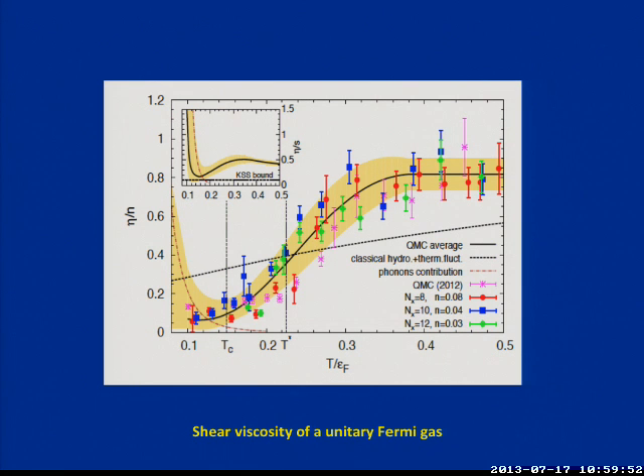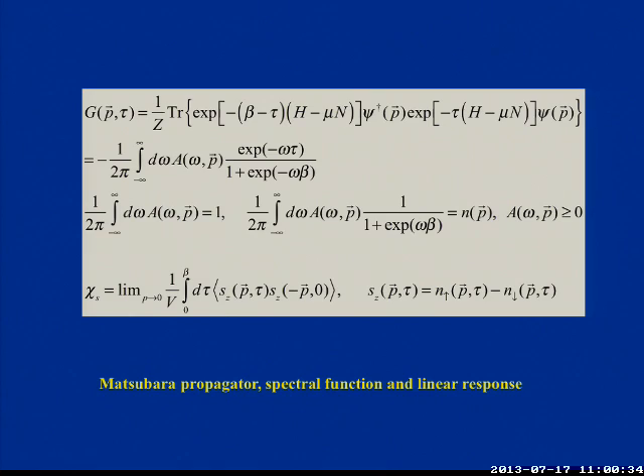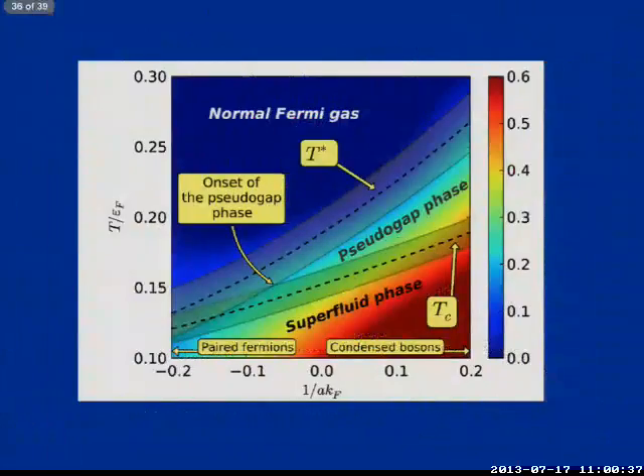One thing which was also calculated is the shear viscosity. You probably heard there was a lot of discussion, especially about the quark gluon plasma, after the work of Son and his two collaborators, that the shear viscosity has a lower limit. That lower limit is somewhere here. The quark gluon plasma is the perfect fluid because its viscosity almost reaches this Kovtun Starinets Son (KSS) limit. We calculated this by looking at the response, as we did, for example, for spin susceptibility, which I'm going to show you in a second, but using the stress tensor. And this is how you calculate the